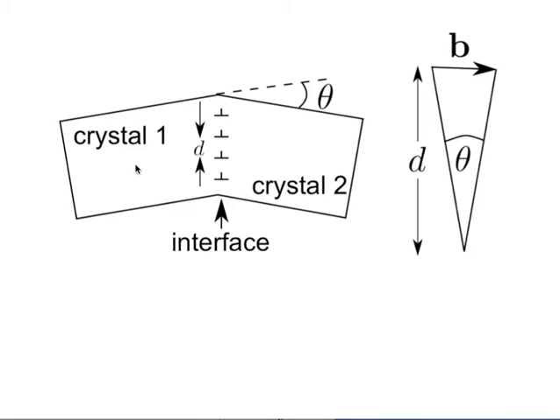So we've got crystal one and the second crystal, and there's no gap here now. We've filled it up with extra half planes, which fill up that wedge-shaped void when we tilted one half with respect to the other. Because this is a tilt interface, a single axis and a single rotation, we only need one set of dislocations to accommodate the misfit between the two crystals. The array of dislocations, the line vectors, are poking into the plane of the board. And those dislocations will have a certain spacing d.